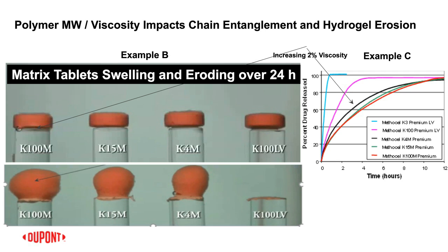We took a time zero, if you will, if you see the picture in the middle on the left. Those are essentially the tablets right after they have been placed into the dissolution media, and we've just taken a picture of it. And then the picture right below it, you see those tablets after 24 hours. And you see, for example, on the right-hand side, the tablets containing Methocel K100LV, the lower molecular weight grade, are completely eroded away within that 24-hour period. And then you see a rank order to the left of that as you go from low to mid to high molecular weight grade. So next in line would be the K4M.